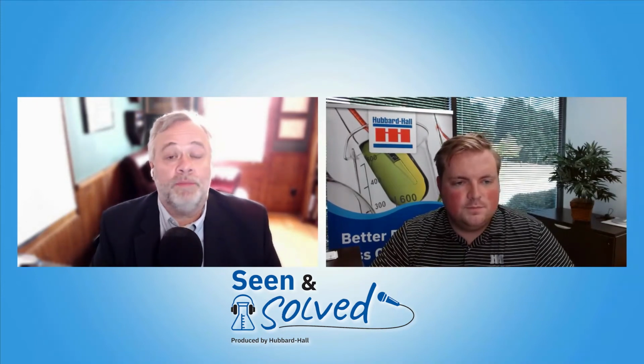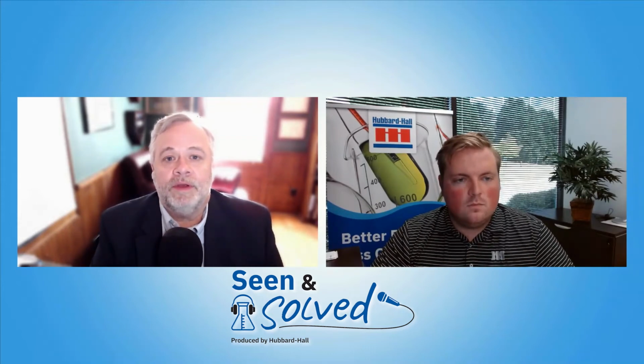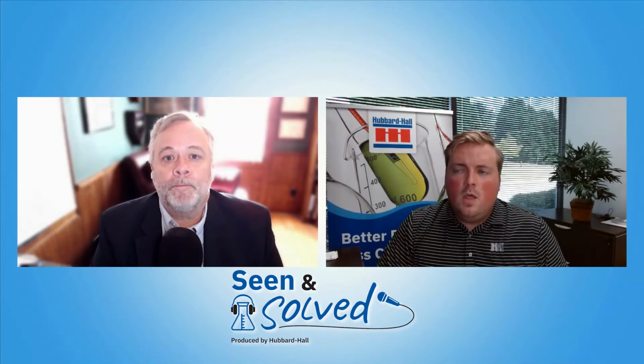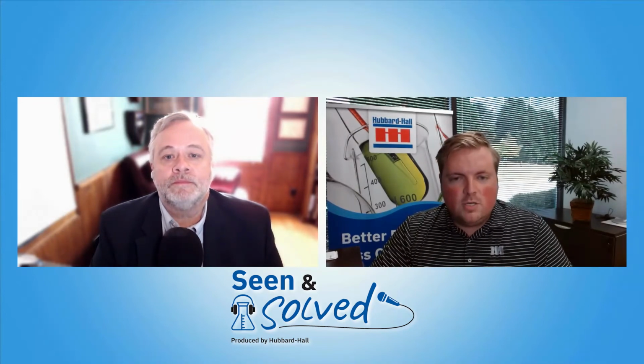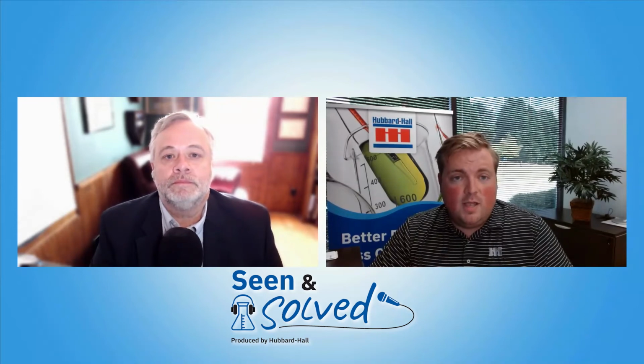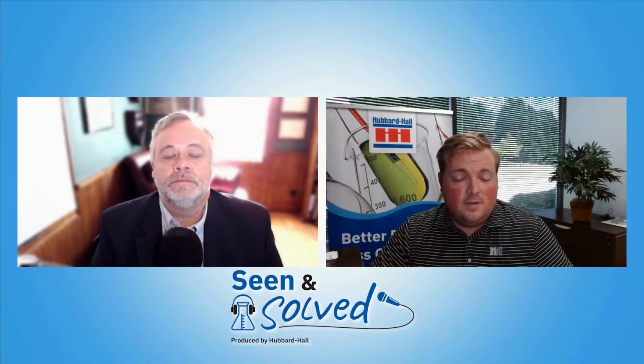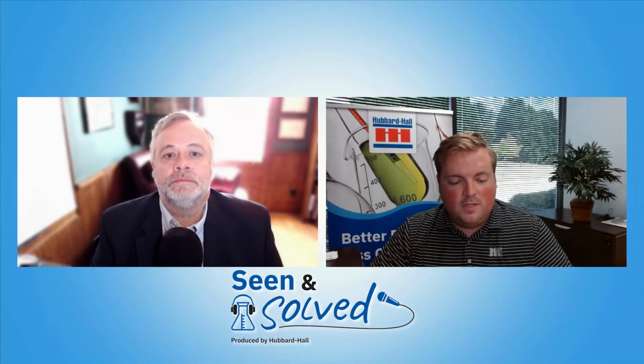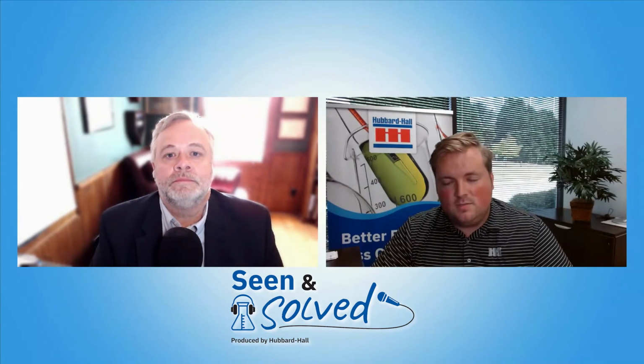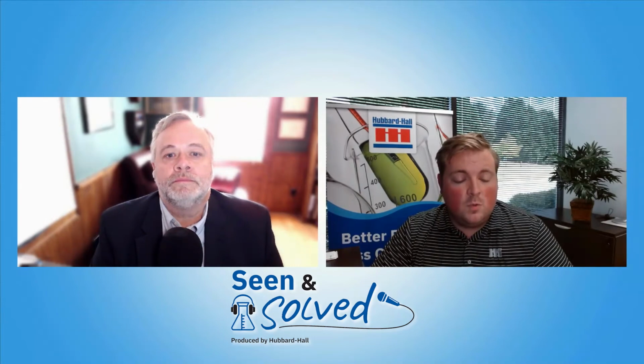Gotcha. Now, are there any post-treatment concerns? We talked pre-treatment, but is post-treatment with this unique? Sure. So, like I said, these coatings in general provide you with a good bit of anti-corrosion protection and some of the mechanical properties that we talked about earlier. You can augment the properties of that coating by using a sealant or a post-dip, such as either a water-soluble or water-displacing oil on the surface.